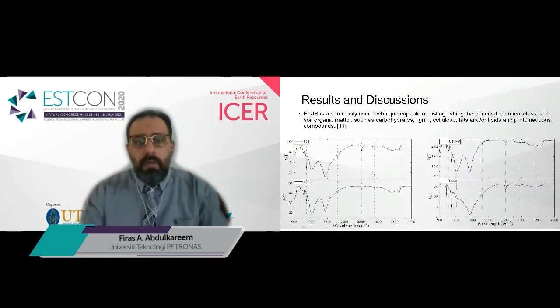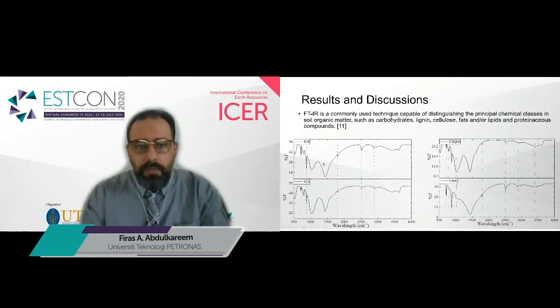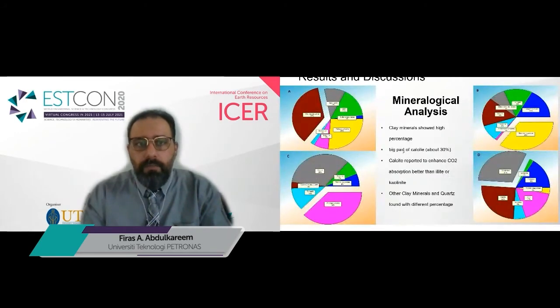So according to the functional groups from the Fourier transform infrared analysis, we can see that the peaks shown for the 4 samples are more or less identical, referring to some carbohydrates, lignin, cellulose, fats, and some lipids, which was actually in agreement with the results obtained from the X-ray diffractometer, which represents the mineralogical content of the shells.